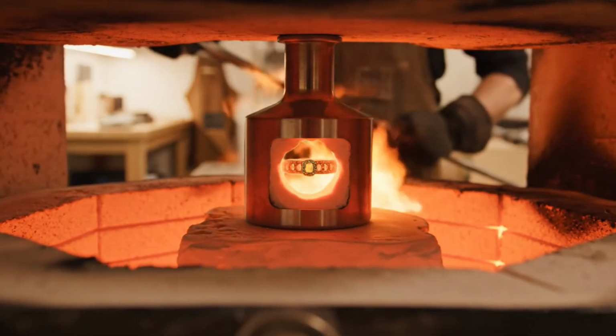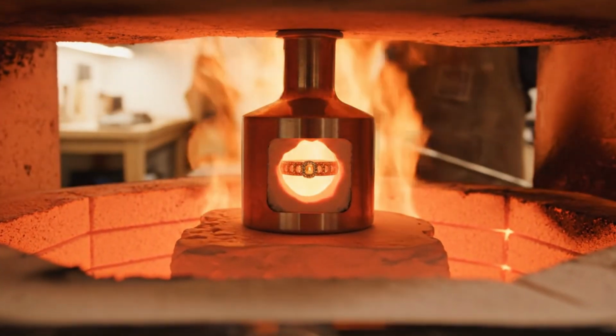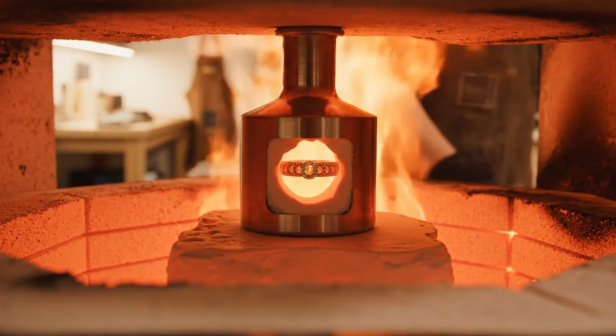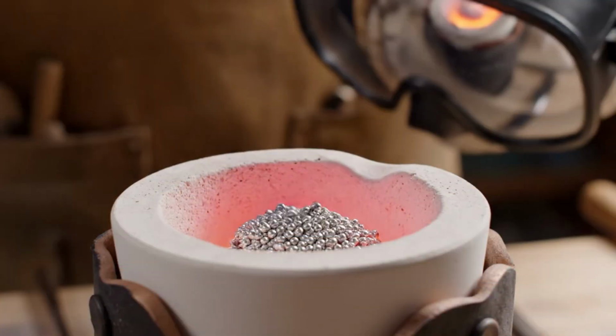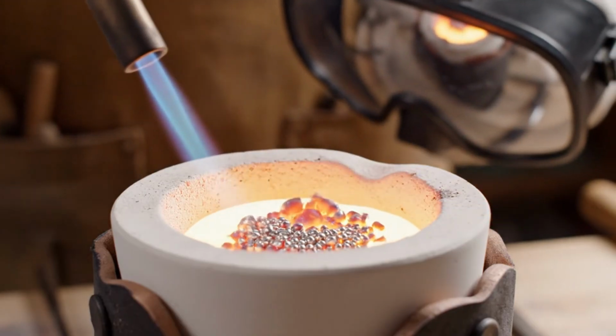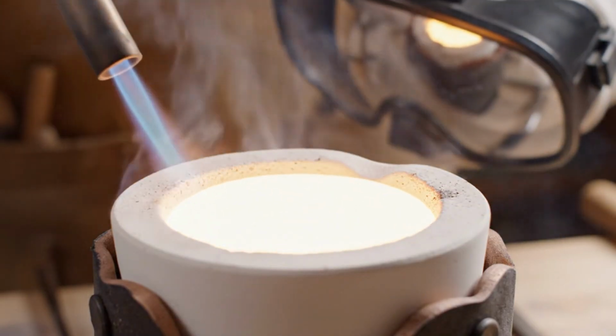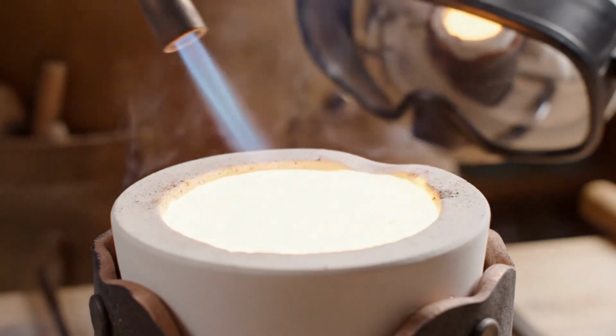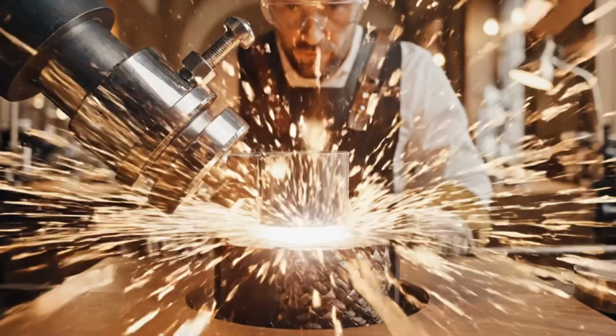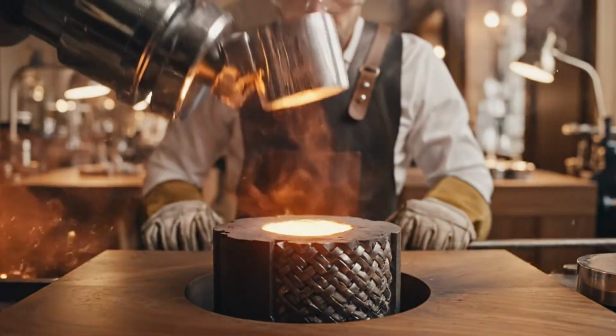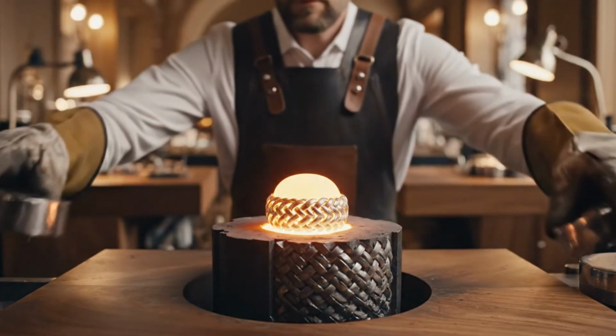The flask enters the kiln for the burnout cycle, where the wax melts away completely, leaving behind the negative space for metal. The crucible heats the platinum grain to over 3,000 degrees, turning the solid gray pellets into a blinding pool of liquid. Centrifugal force slams the molten metal into the hollow cavity, filling every detail of the basket weave pattern in a split second.